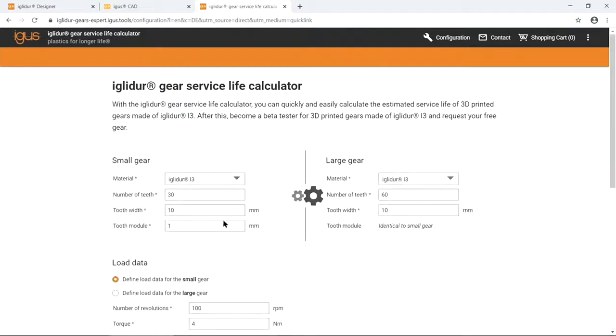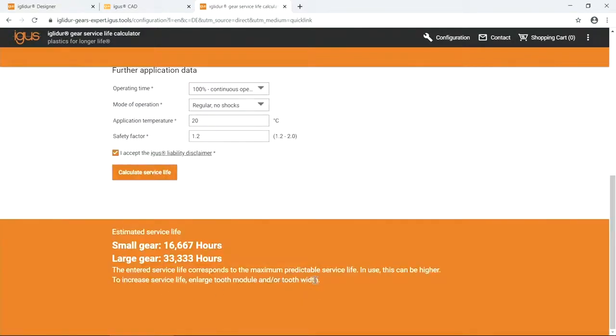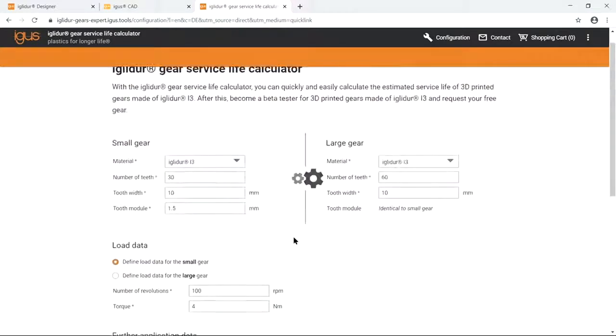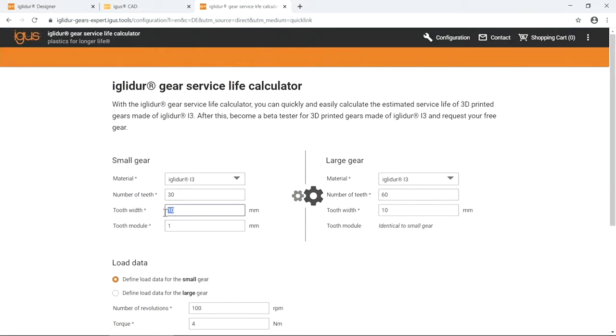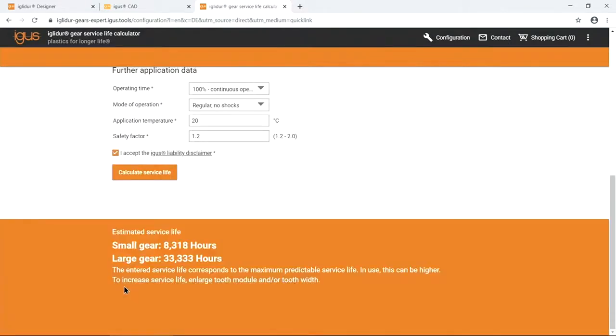Because now you can start changing the values here on the top, like the tooth module. Module is for the size. If I'm increasing to like 1.5, then again I have a really high lifetime. But if I'm increasing the modulus by factor 2, the gear also gets bigger by factor 2. You do not always have this space. So maybe you start by increasing the width, which doesn't make such a big difference. Let's say from 10 to 15 millimeters. And then, yeah, we also have again a much higher lifetime here. And you see you can not only use the tool to figure out the lifetime for your application, you can also use the tool to check what you need to change to have a good lifetime for your application.